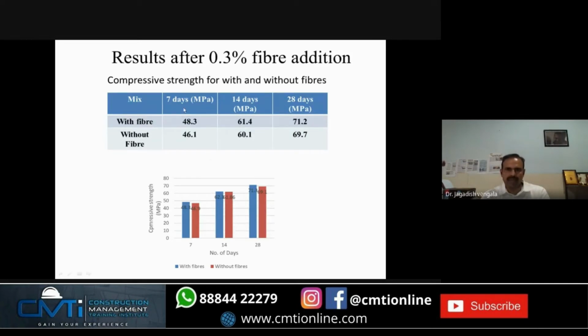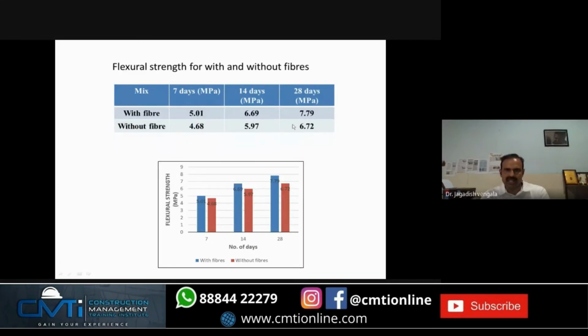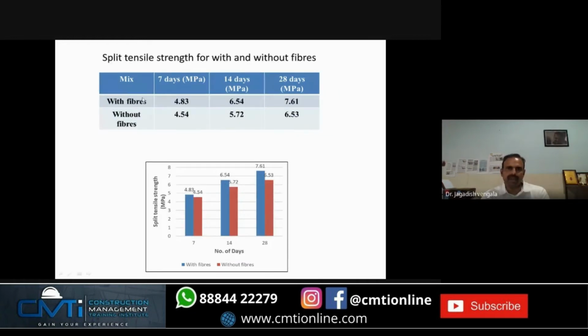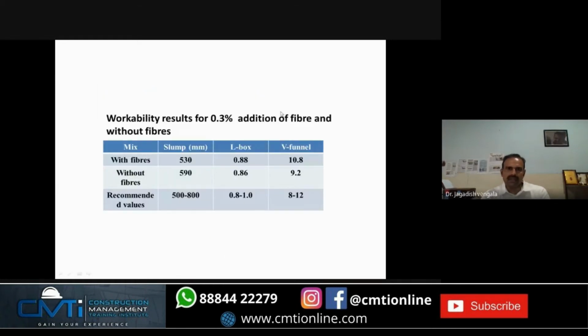So with and without fiber, you can see the compressive strength values. You can see the flexural strength values. There is a little improvement in flexure when you add the fiber for the SCC. And this is the split tensile strength values with and without fiber. This is workability results, because workability reduces when you add the fiber. Fiber is the finest particle, it occupies, that means the surface area increases, so your slump reduces.